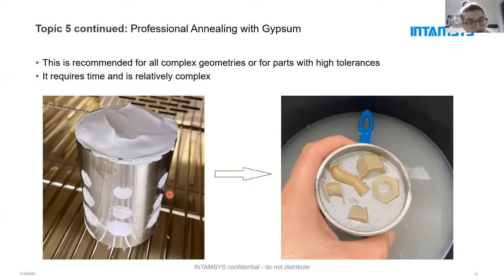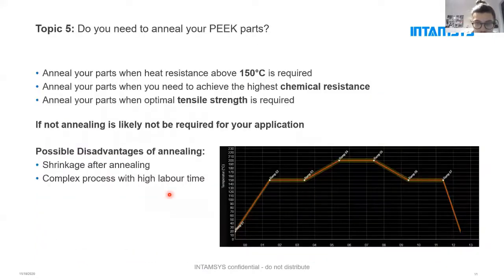it out. If you look back, here is one curve how annealing looks like. Especially the ramping is very important to get a consistent crystallinity. So slow ramping up and slow ramping down is very important for good annealed results. For the top temperature, we use 200 degrees, and our start and finish temperature is 150 degrees, as this is still a little bit below the HDT, where the part starts to get softened.